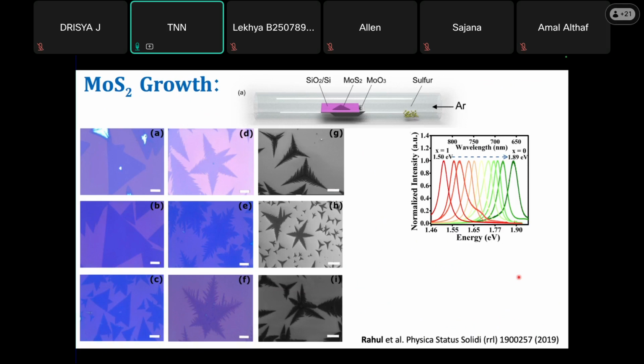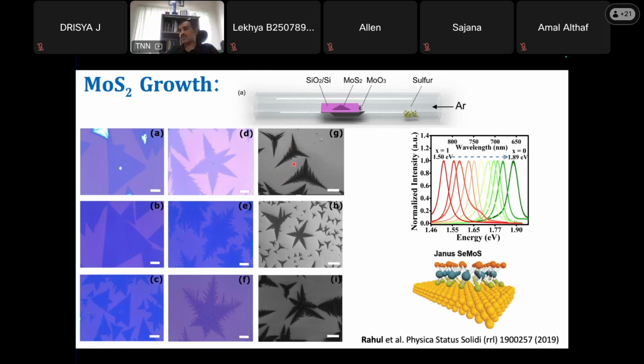Now, how do you do growth? We can grow such very nice TMDs, transition metal dichalcogenides of various kinds, in the lab using chemical vapor deposition. You can control the thermodynamics and kinetics, and control the nature of the crystal, etc. So this is an MoS2 monolayer crystal, and this is the same monolayer crystal you can engineer by controlling the molybdenum to sulfur ratio during the growth.